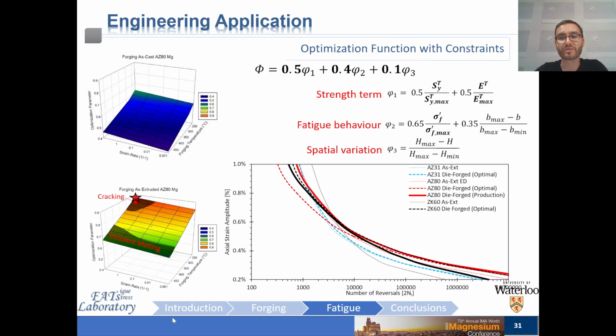And then finally, the practical constraint of the forging load or the forging press capacity that can prevent forging at very low temperatures, even at comparatively low strain rates. So we might want to impose that constraint there. And this effectively limits our processing window to exclude this gray area, and we will generally constrain the optimum forging condition to be a compromise of all of these constraints, as well as these relative parameters or these thermomechanical processing conditions. You can see how the optimum condition here would shift then.